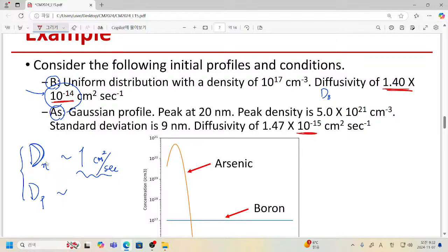And you know that this is not for 300 Kelvin. I'm not talking about room temperature. At room temperature, we have even much lower diffusivity. That would be a really meaningless number. This number is taken from, for example, about 1000 Celsius, which means that this is the real situation. We heat the wafer.